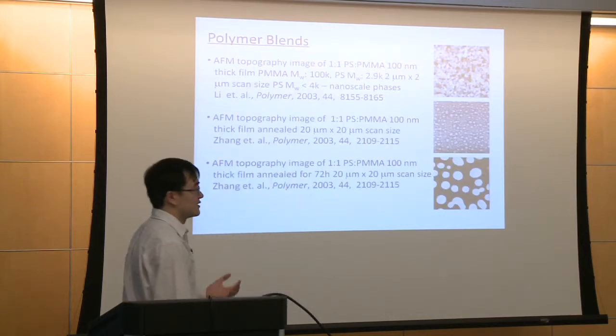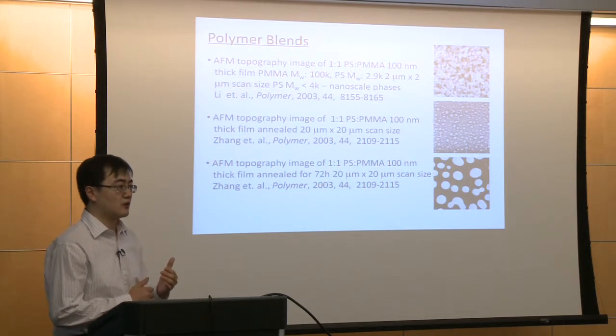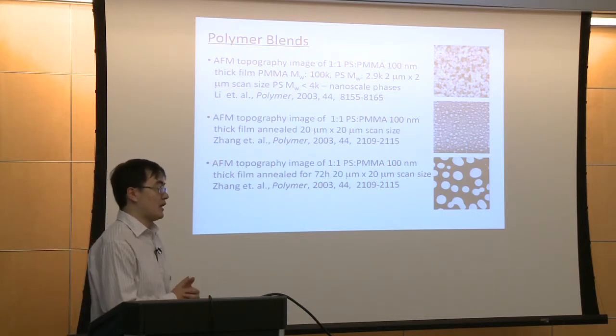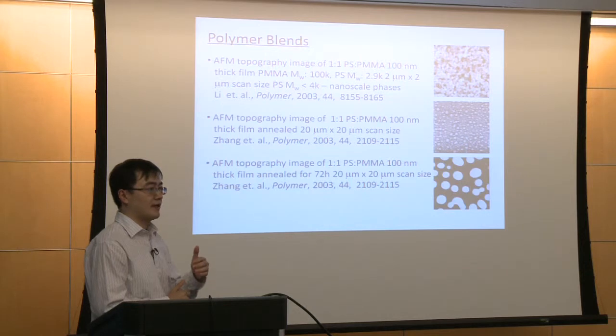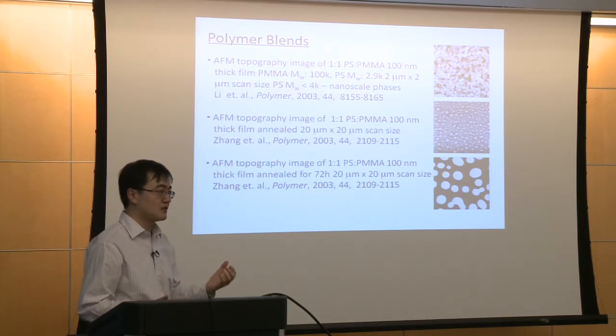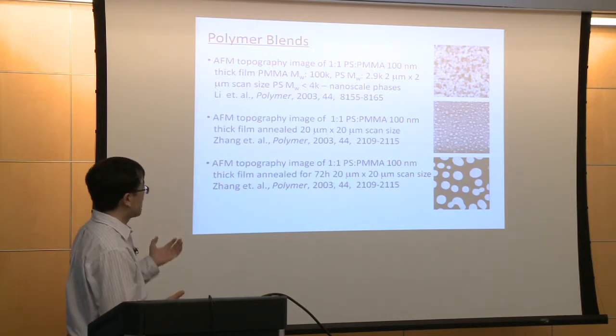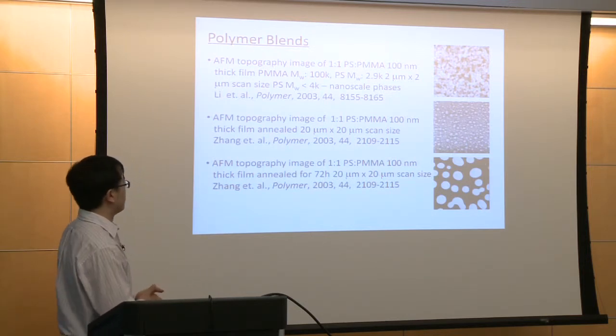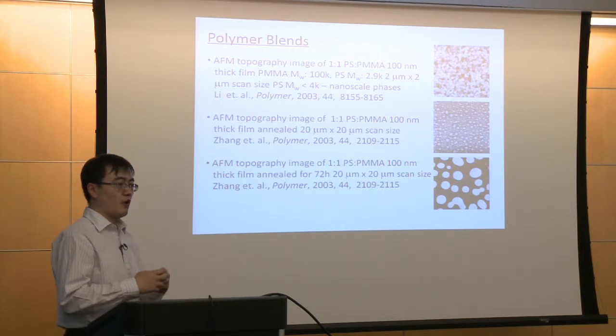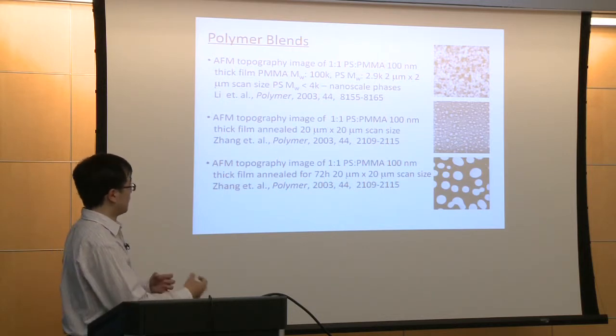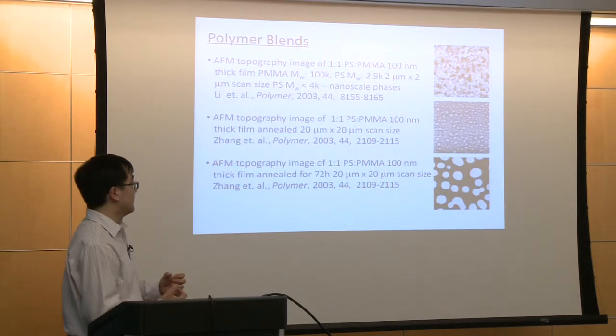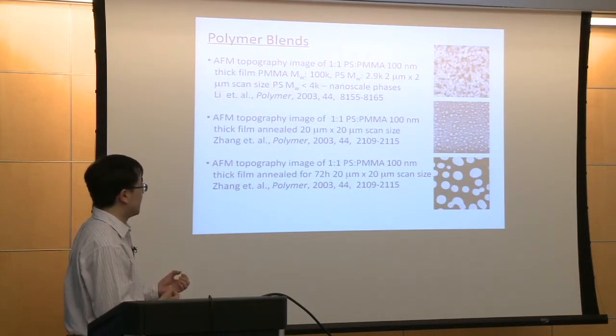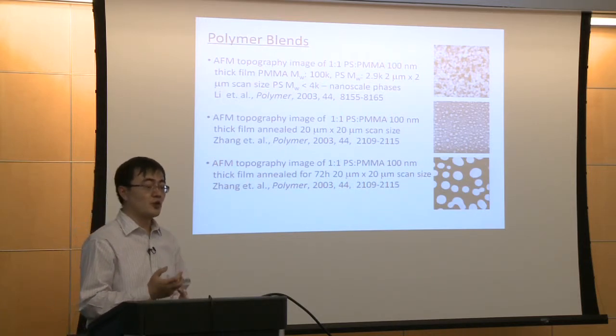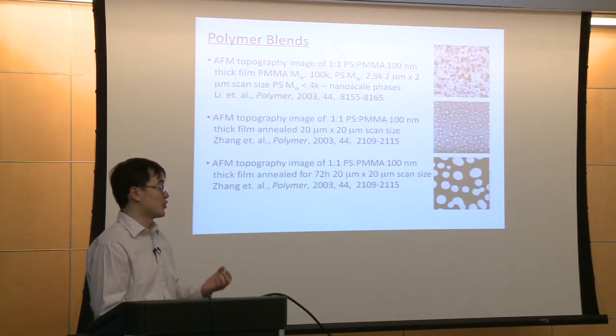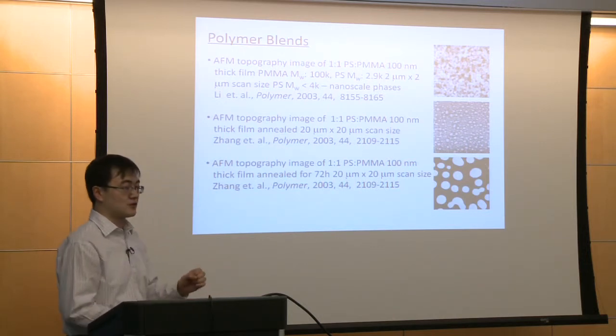Okay, so this idea is very great to confine the material, but we are considering whether we can build up the same structure without the template. Based on the previous references, when you mix two different polymers together and anneal it, there will always be phase separation on the surface. And by controlling the ratio between two polymers and controlling the annealing time, you can easily control the domain size on the surface.